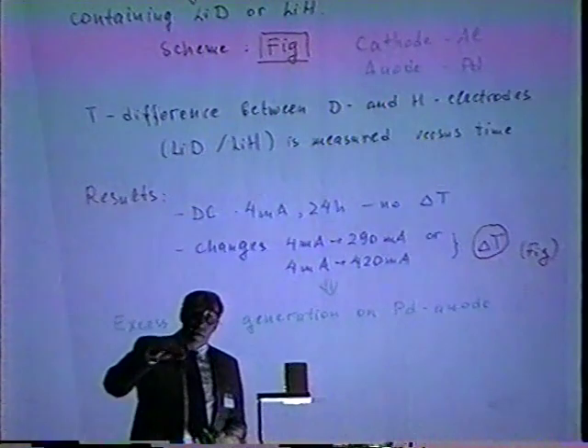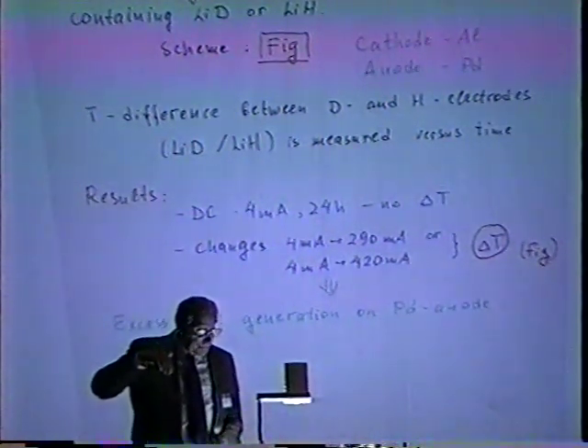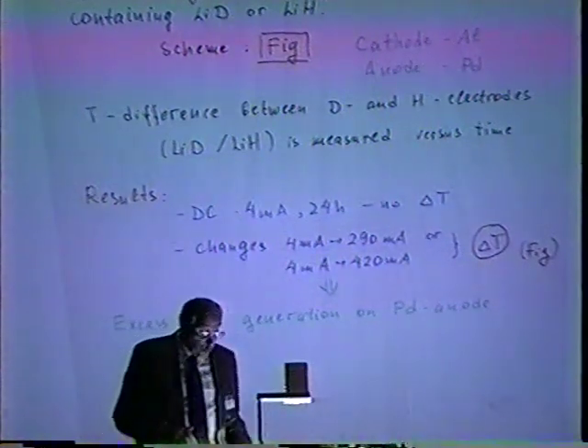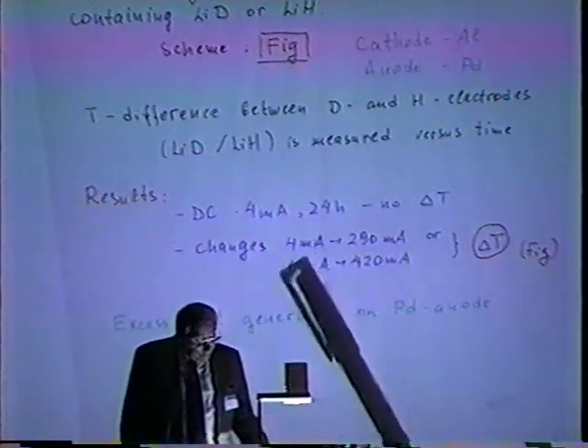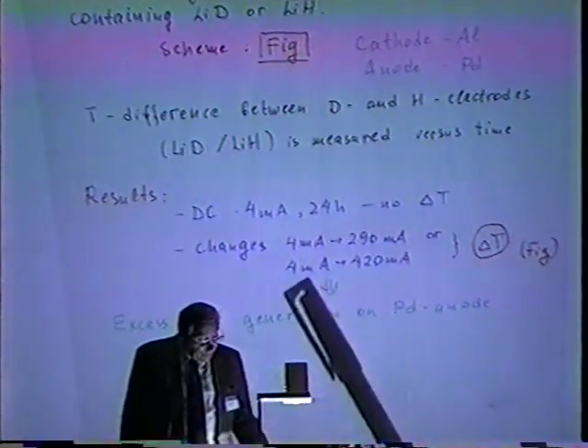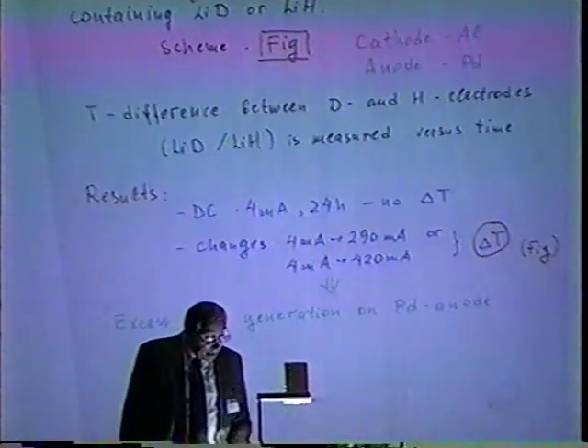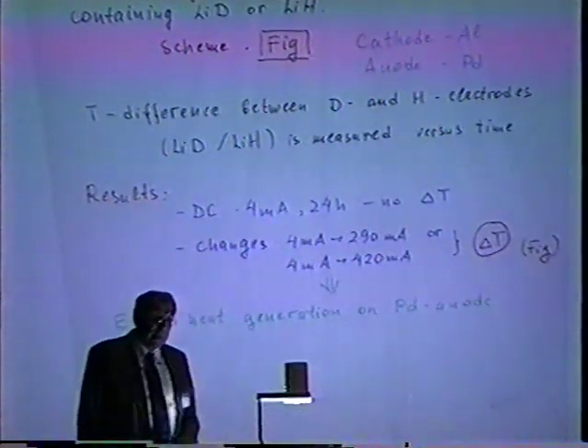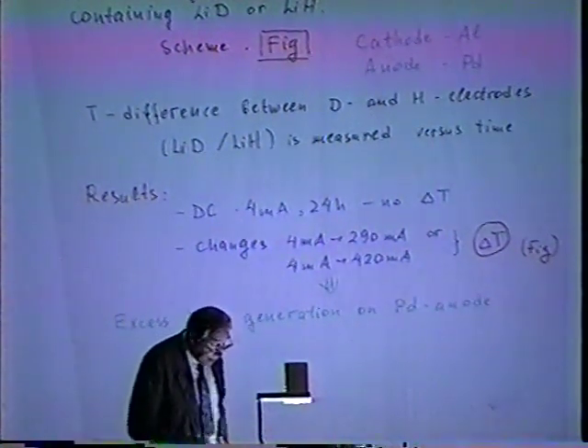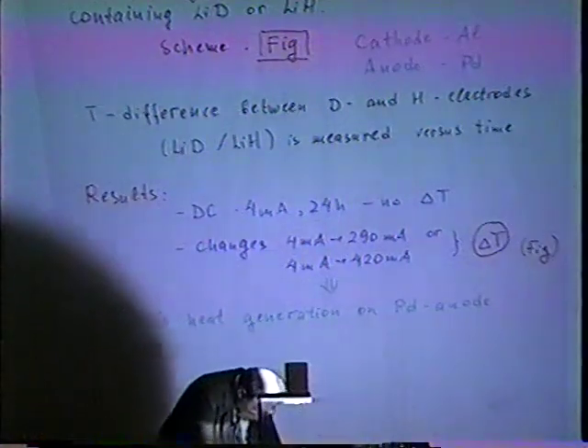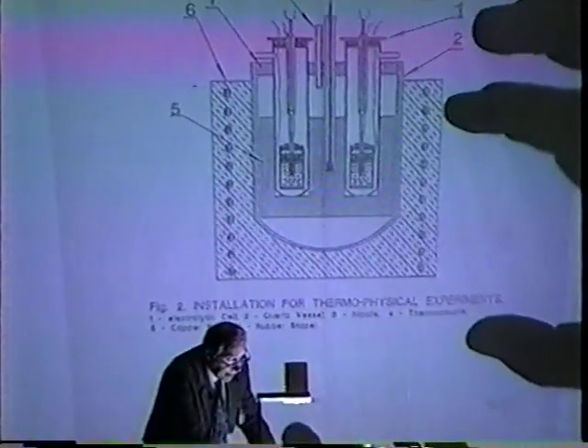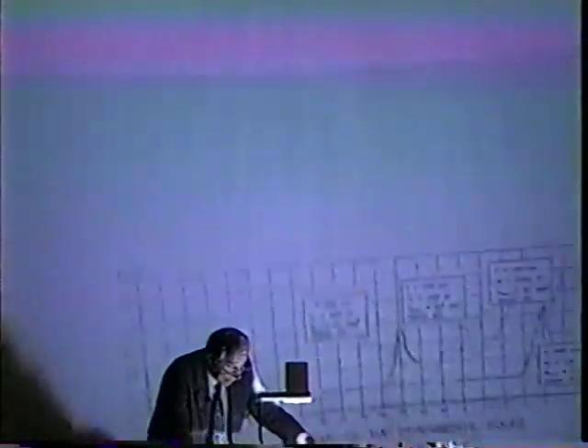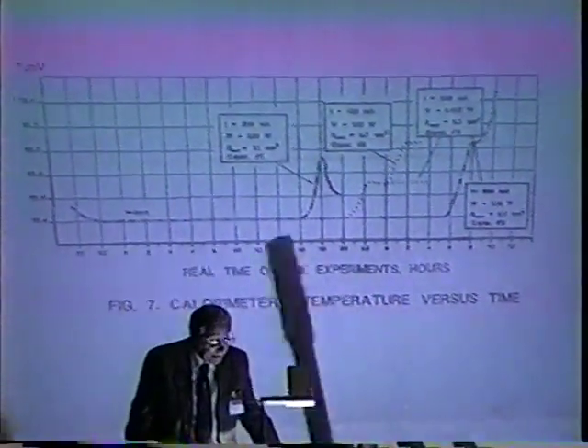However, if they used variable current, I'll show you the picture, varying from 4 to 290, from 4 to 420 milliamps, then they observed a really sizable increase of temperature, a heat effect. So, pictures. These are their two cells with the deuteride and hydride materials. And this is the result of the calorimetry. You can see some increase of temperature.